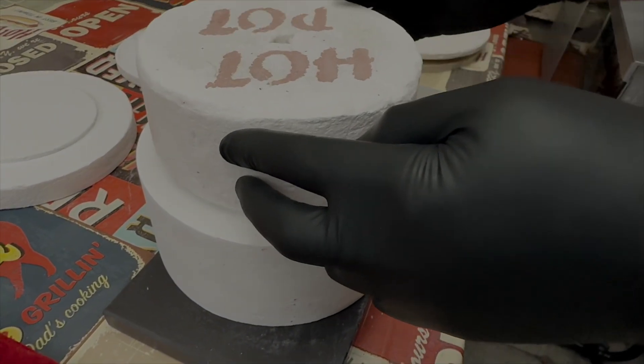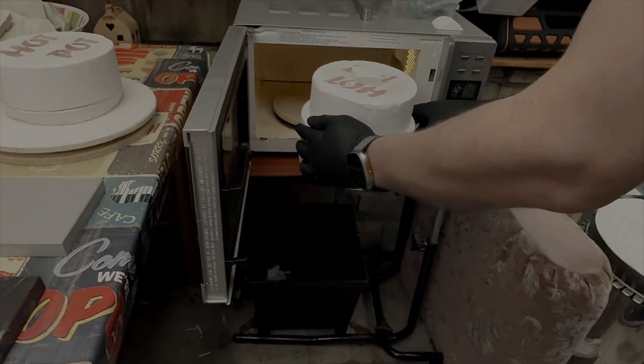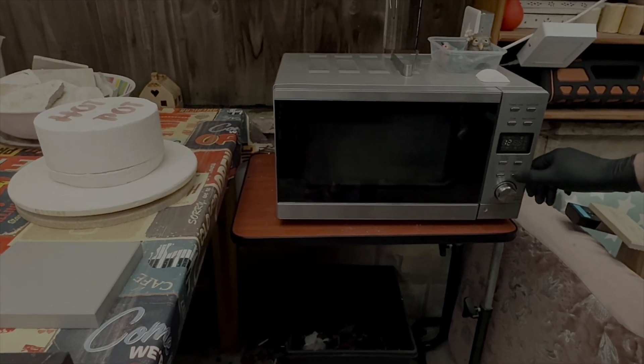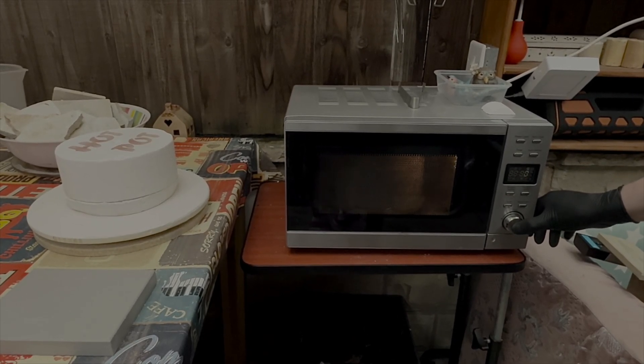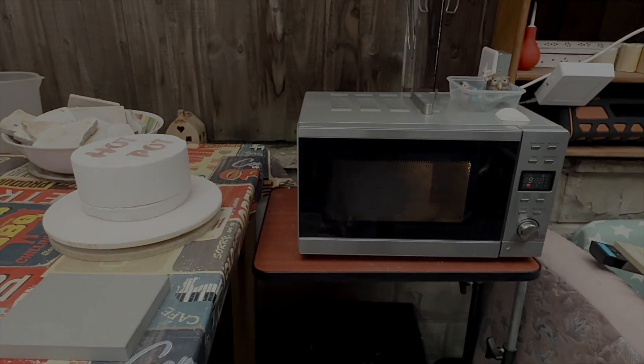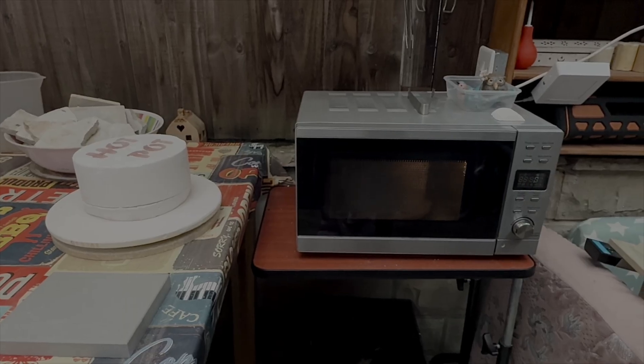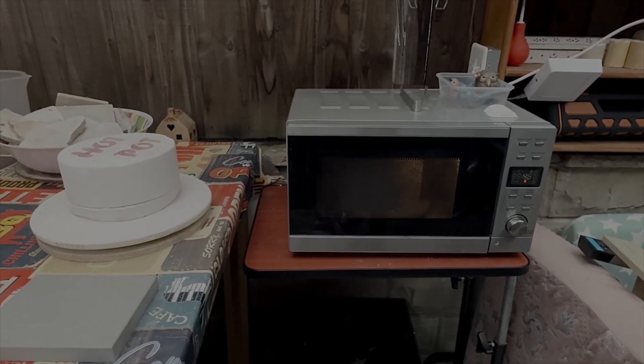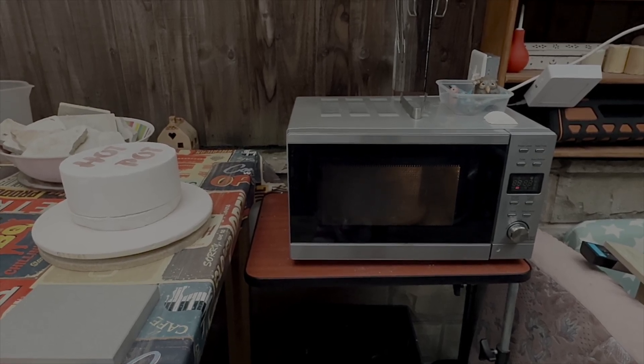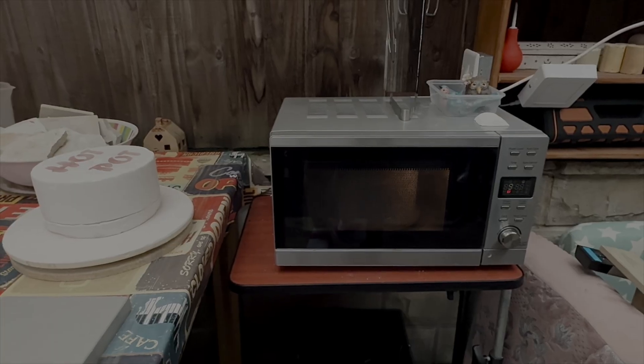We're going to do a little demo with the piece I have — it's a little whistle bird. The best thing is to experiment with your own microwave and kiln. I'd do it in increments of five minutes. You can do a preheat with just the kiln on its own for five minutes, then put your piece in. Make sure the glaze is dry. For me, I usually fire pieces for 20 minutes and then an extra five or ten minutes after that.